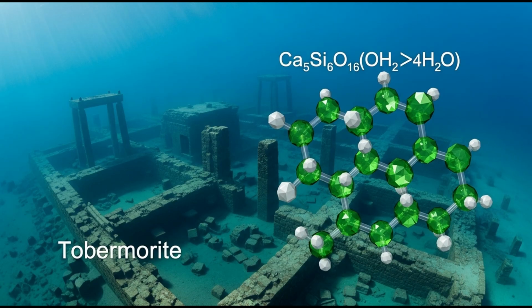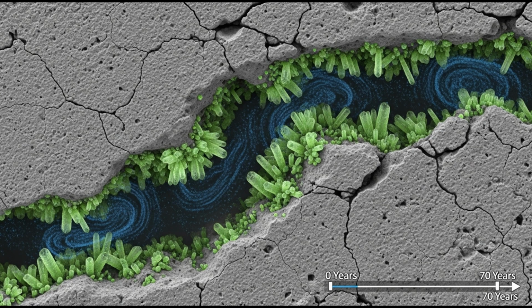Tobermorite formation. Tobermorite is a rare calcium silicate hydrate mineral, with the formula Ca5Si6O16(OH)2·4H2O. It forms only under specific conditions: elevated temperature, or prolonged seawater interaction with volcanic ash. In Roman concrete submerged in seawater, pozzolana reacts with calcium from lime and with silica from the ash itself. Seawater provides additional calcium and alkali ions, magnesium and sodium. These modify the reaction environment.